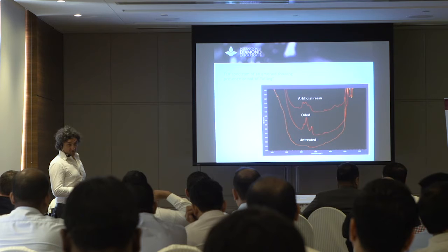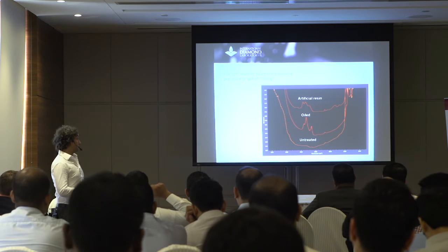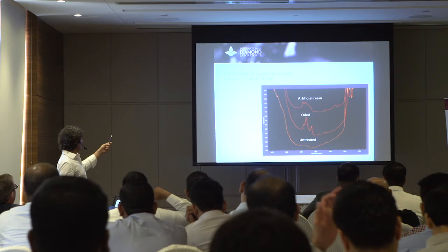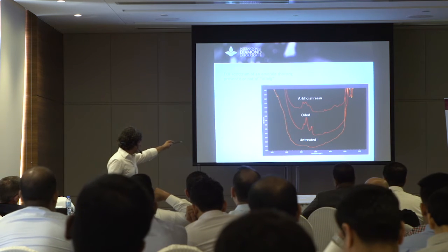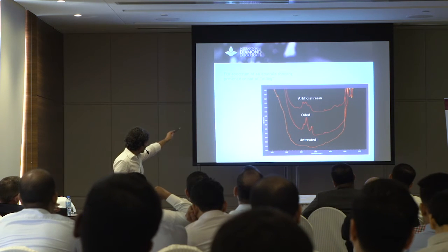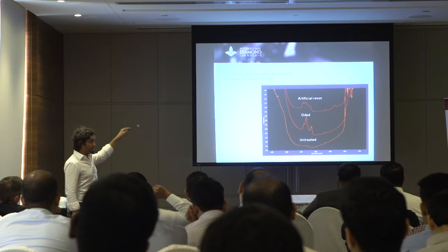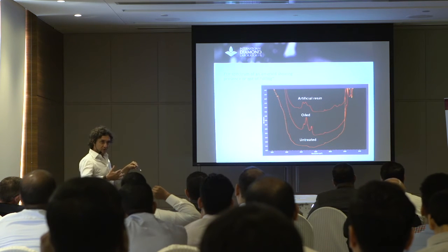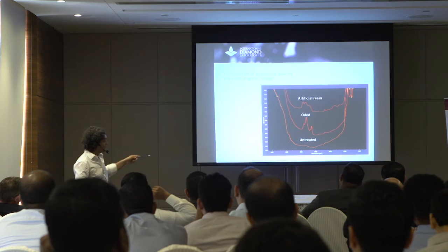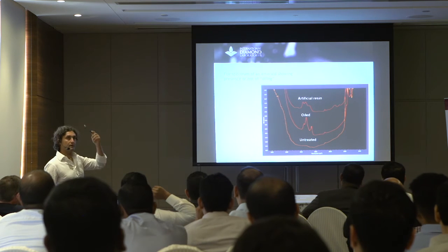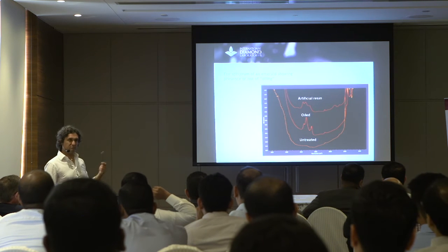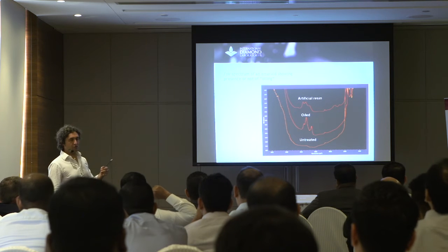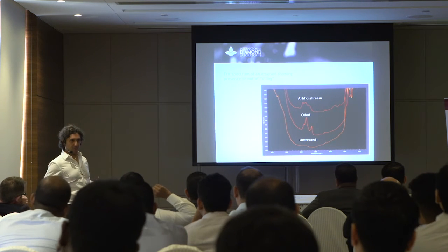I can have an idea on the microscope, I can see, but the infrared spectrometer can show me if the stone is untreated, if the stone is being oiled, also how much it is oiled, and or if the stone is treated with, let's say, optical artificial resin. It's a kind of resin.